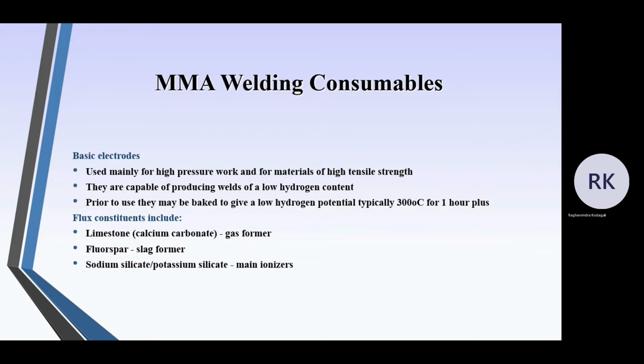So the basic electrode is mainly used for high pressure work and for materials which are high strength steel. So obviously it will be a little bit expensive. They're capable of producing welds with low hydrogen content, and that's why crack prevention is there in this. Prior to use, they may be baked to give a low hydrogen potential, typically 300 to 350 degrees for 1 to 2 hours.